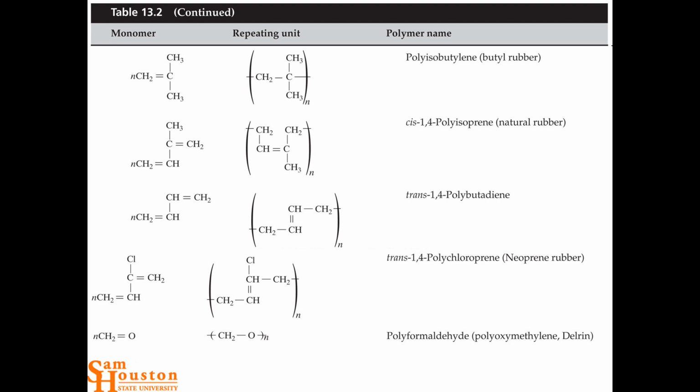And so if you're working with organic solvents, never use latex gloves because they're not protecting you at all. Okay. Always use the nitrile gloves. Those nitrile gloves, the nitrile groups are more chemically inert and more resistant to organic solvents, and so they're more impervious or resistant to organic solvents. So the nitrile gloves will not absorb organic solvents as much as natural rubber. All of these polymeric materials have a breakthrough time, and it's based upon the thickness of the glove and the material of the glove.